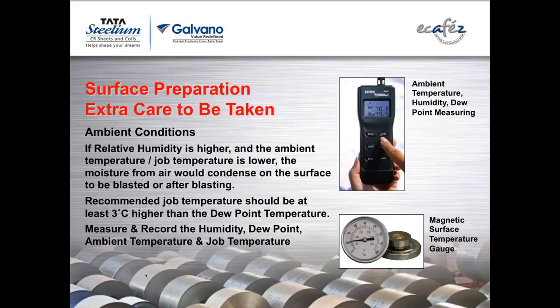This is what happens on your jobs when you blast them. So we usually recommend checking ambient temperature and relative humidity, and from relative humidity you can find the dew point. Dew point is the temperature at which water vapor will condense into water. And we also check the job temperature.